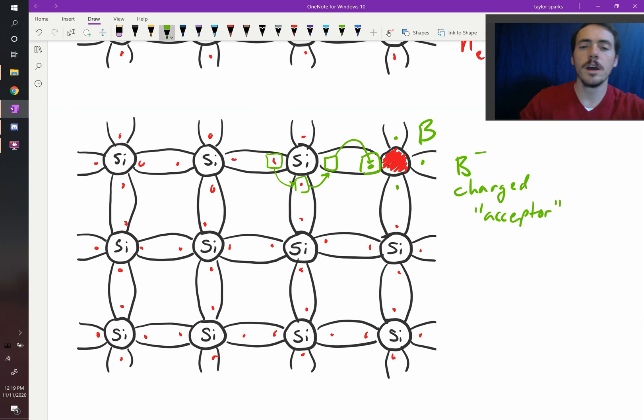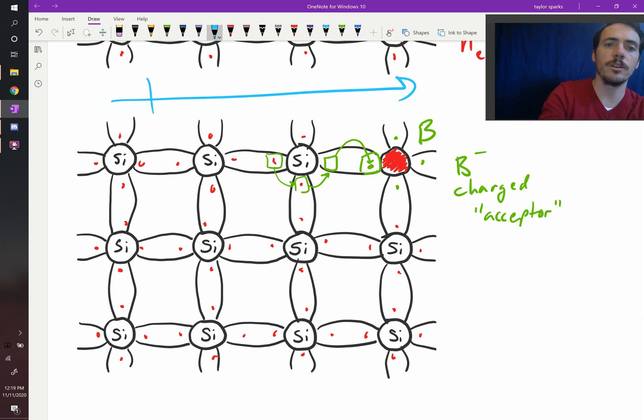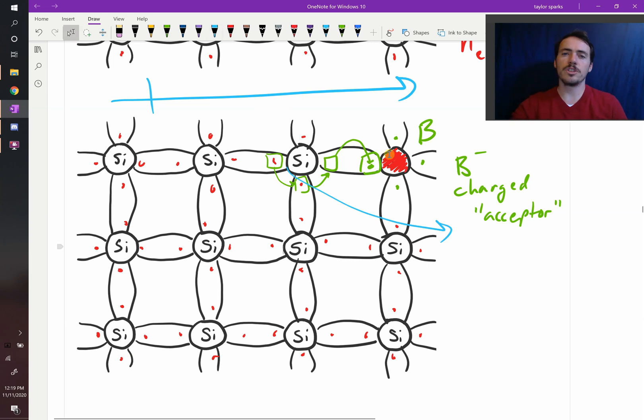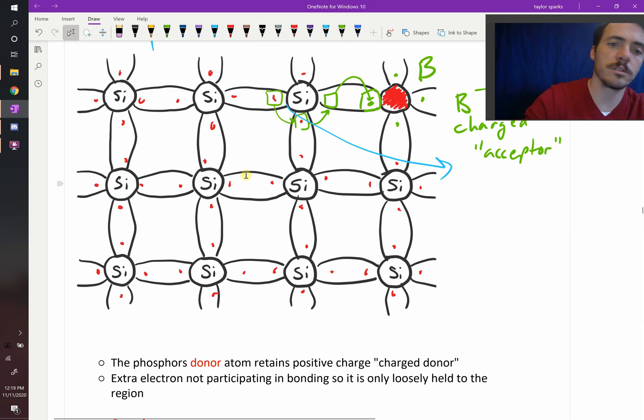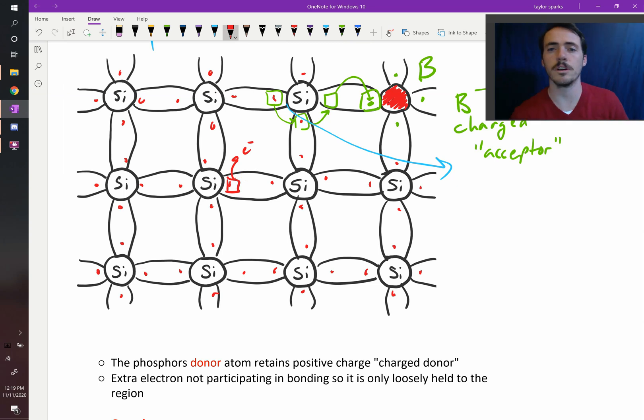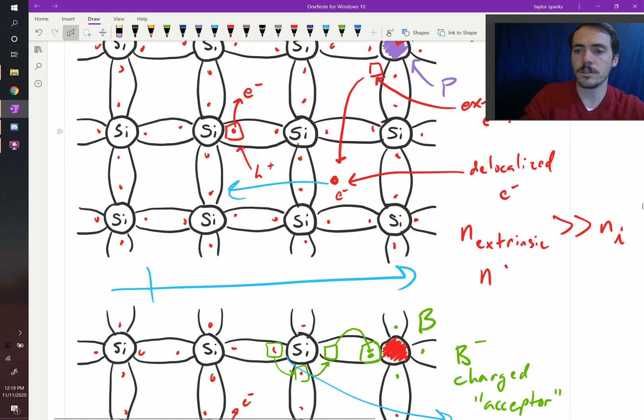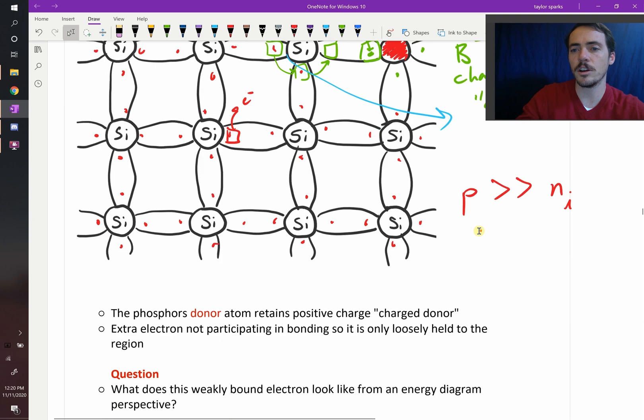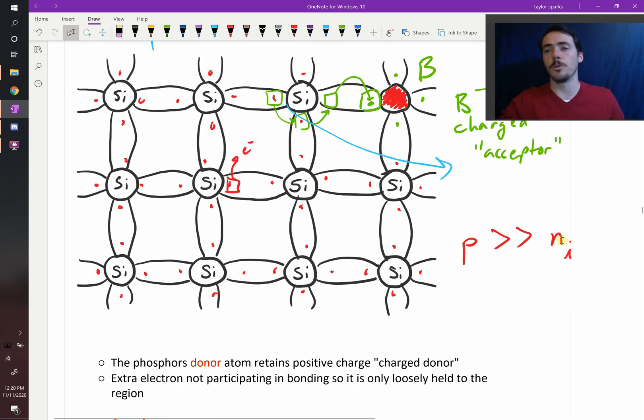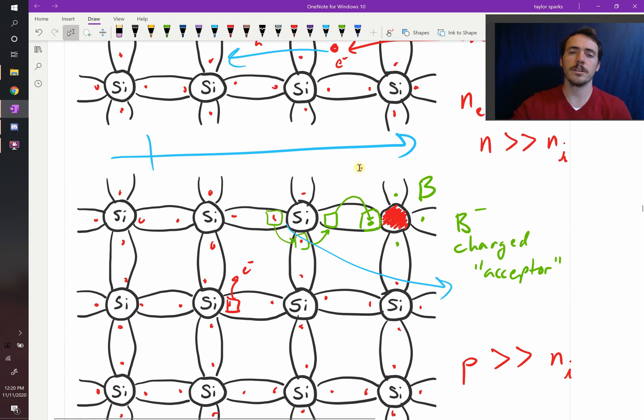That hole is able to have another electron occupy it and move, and then another can come and occupy it, so it can move through the lattice. In an electric field, this hole is able to move. You can also have intrinsic contributions — a bond splitting into a free electron and a hole — but we're assuming that P, our extrinsic concentration, is much greater than our intrinsic contribution, so we ignore it. So that is how you dope things: if the dopant is to the left on the periodic table, it dopes it p-type; to the right, it dopes it n-type.